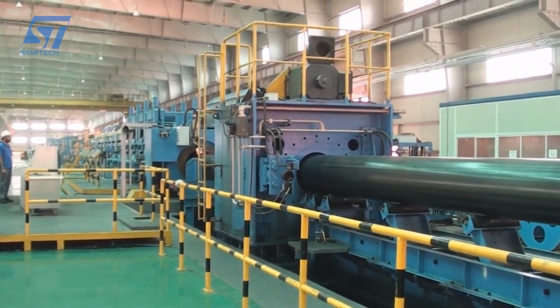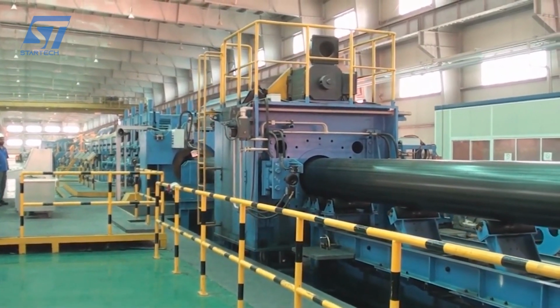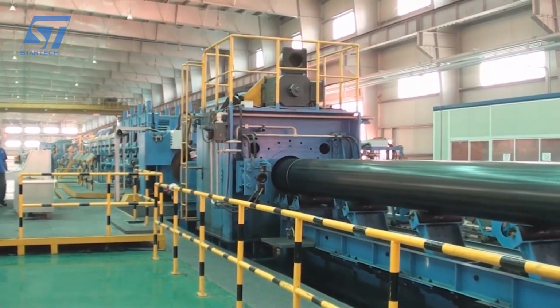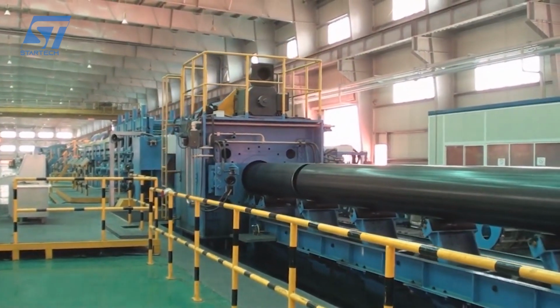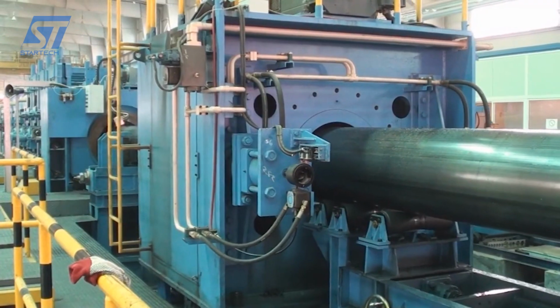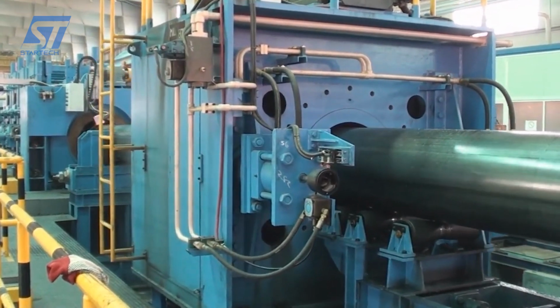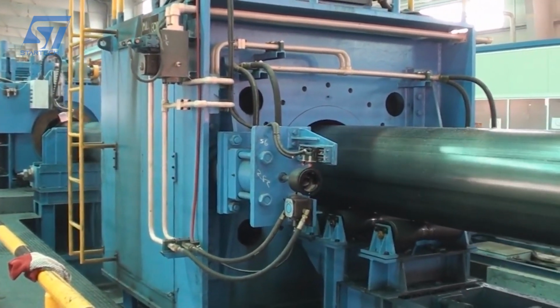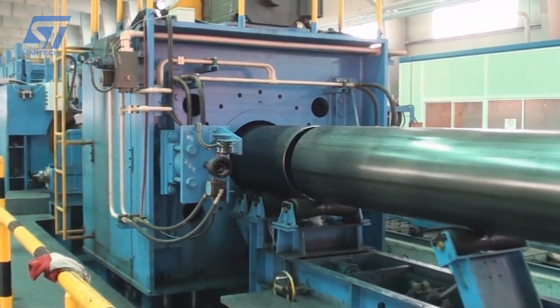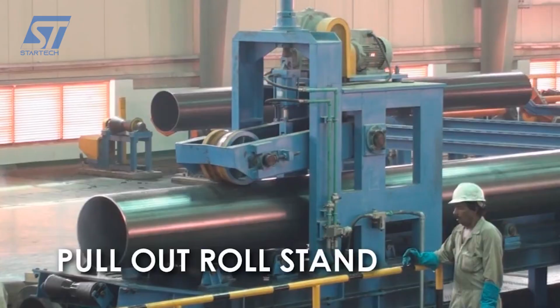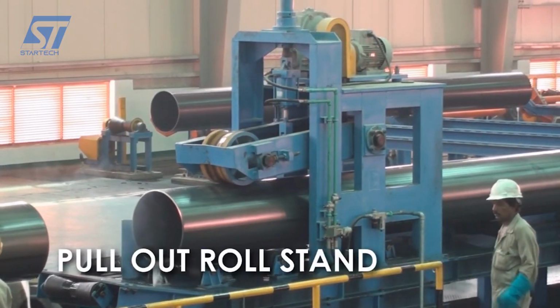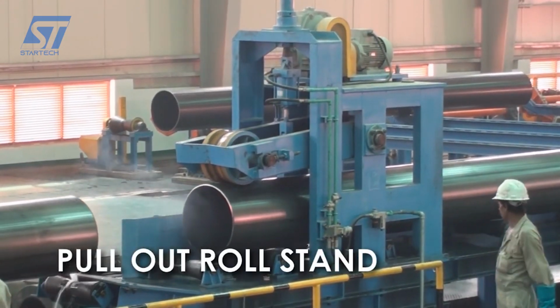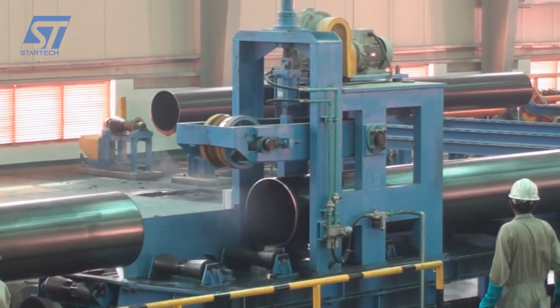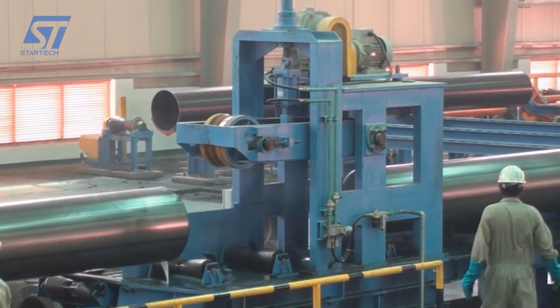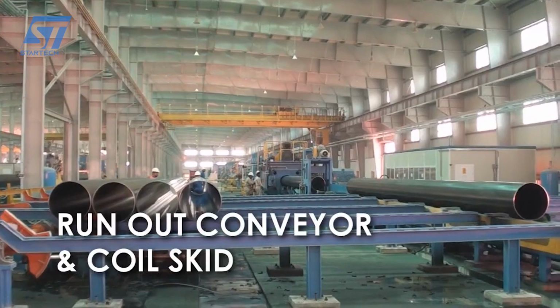The steel edges, after being shaped, are passed through the high-frequency welding system. The temperature control system ensures a uniform weld, without voids or cracks, increasing the mechanical strength of the pipe. The pipe is cooled by water or air, stabilizing the size and structure of the material. The final shaping roller ensures the specifications of the diameter, angle, and flatness of the product. The pipe is cut to the required length by the automatic cutting system without deforming the product.